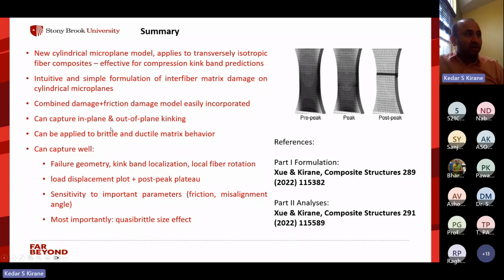So to summarize the microplane model, it is basically a new formulation. It has two length scales, and its hypothesis is that the failure is triggered by interfiber shear in the direction parallel to the fibers. And so it has combined damage and friction. It captures local fiber rotation, and so it can do both in plane and out of plane kinking. And it was able to capture very well the failure geometry, the local fiber rotation, the kink band localization, and also this post-peak plateau in the load displacement plot. And most importantly, it was able to capture the size effect.